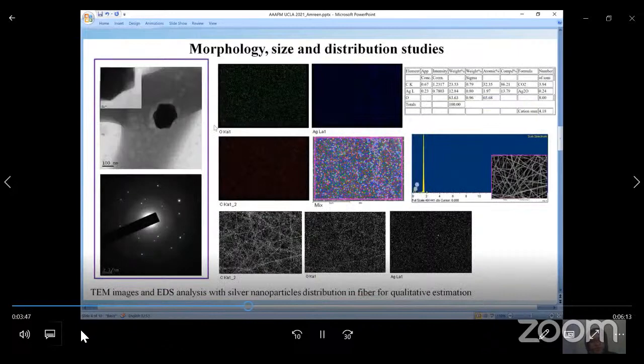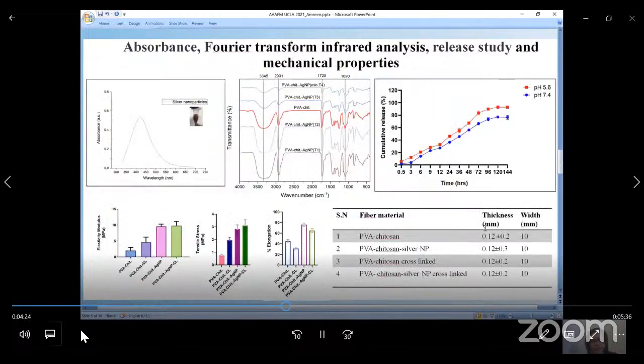Then, in order to see whether the nanoparticles were present inside the fibers, we carried out TEM analysis of the fibers embedded with the nanoparticles. And here are the diffraction images showing that the nanoparticles present inside the fiber are of monodispersed nature. Further, the area spectrum was done with the help of EDS, and EDS analysis showed that the nanoparticles are distributed uniformly inside the fibers. Now, the absorbance of silver nanoparticles showed that the lambda max was around 420 nanometer.